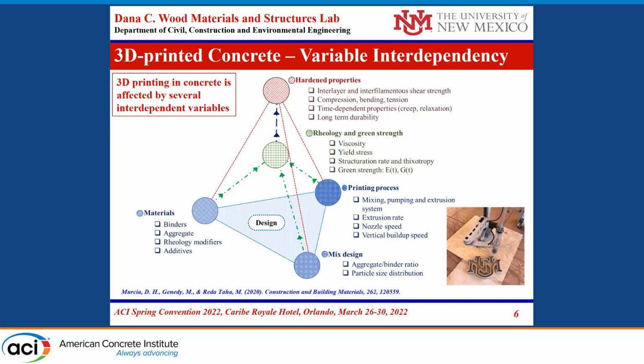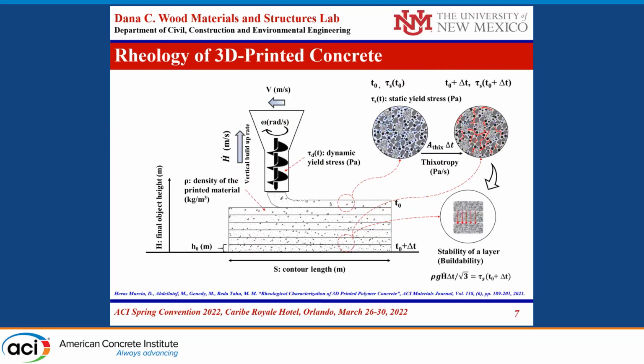Now, this printing process and its different parameters can make a big impact on the mechanical properties of 3D printed concrete. Conceptually, one of the key factors we are looking at is this green strength, and we are looking at how the material starts from being placed, at a time we call T sub 0, the time you place the material, the static yield stress of the material, and how the material, through its thixotropy, which is the property of the material based on its mix proportions and the different materials you have, changes, and how the static yield stress changes with time to T0 plus delta T, which is the time you need to print.